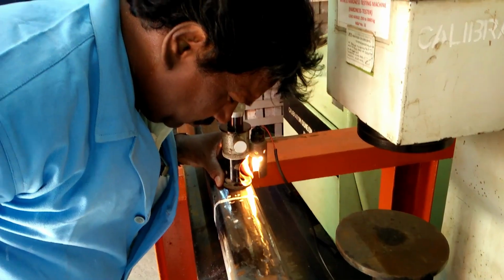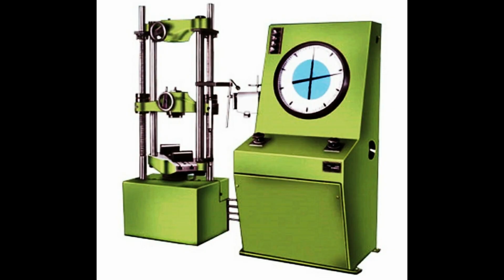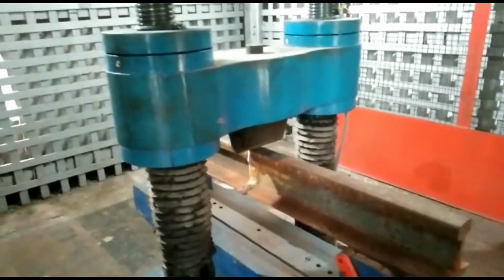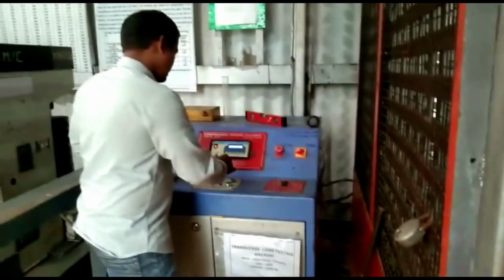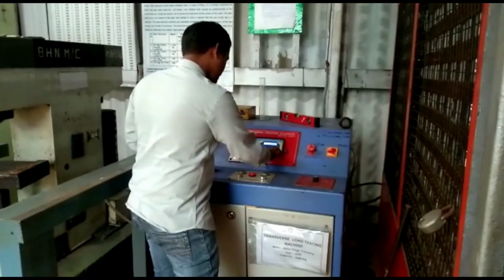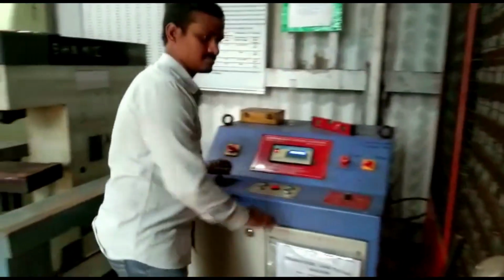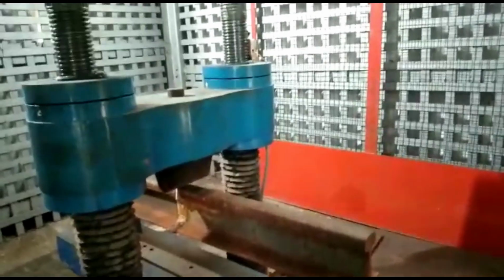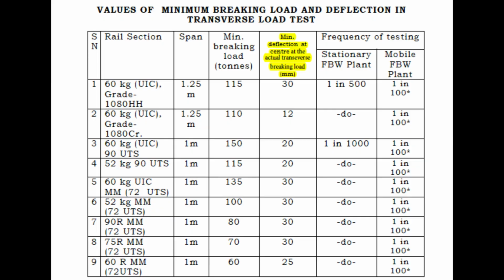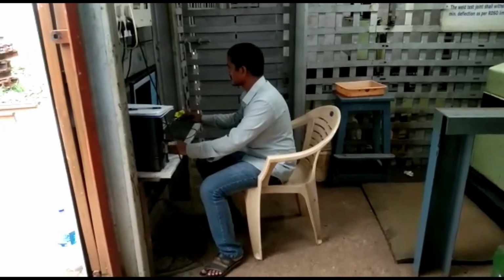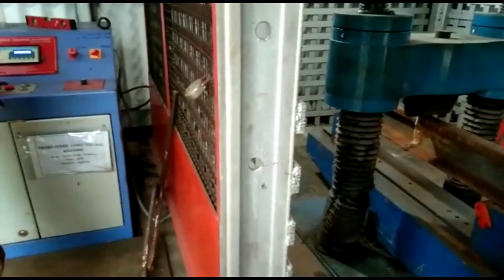Then the transverse load test, its capacity is 200 metric tons. The transverse load test will be continued until fracture occurs or be terminated when the force limit of the press is reached. That is 52 kg 115 tons, 60 kg 150 tons with minimum deflection of 20 mm. But these values are fixed by RDSO and depend upon the metallurgy of the rail. So that is 90 UTS, 72 UTS, MM rails, HH rails, all these are different in applying of load and deflection.